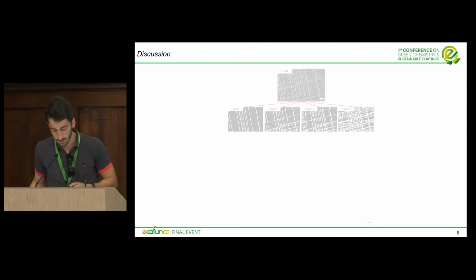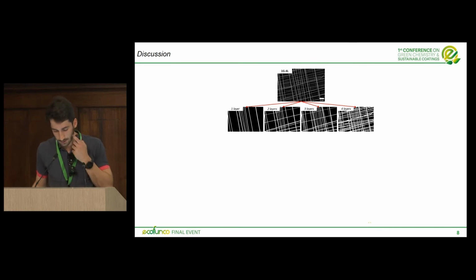So, following these outcomes, we have seen that there is a correlation between geometrical features of the coating and the dimensions of microorganisms. But to fully understand and correlate the bacterial adhesion assay with the wettability results, we use the Cassie-Baxter model. Without going into details, which is also beyond the purpose of this presentation, the Cassie-Baxter model is used to describe heterogeneous surfaces, and to use this model, we have to measure what is called the fraction of solid and the fraction of air, so the porosity of the surface. To evaluate the effective porosity, we designed an image-based approach based on GIMP and ImageJ graphic software. We aimed at measuring the different possible porosities seen by the liquid drop on the surface by assuming different possible penetration levels.